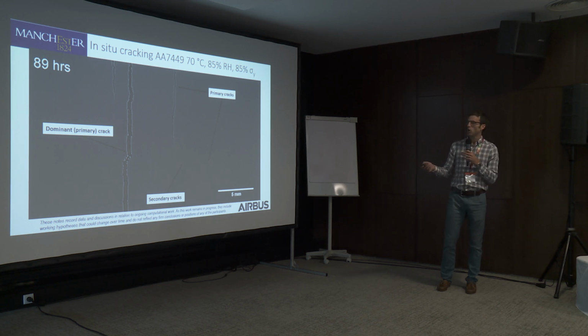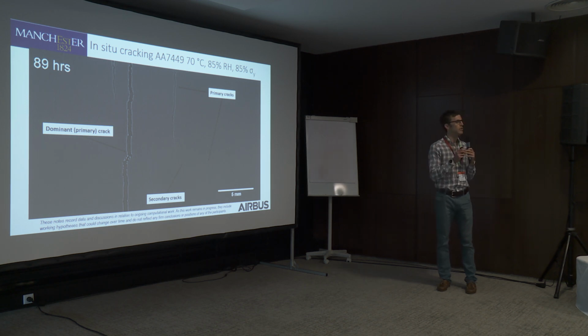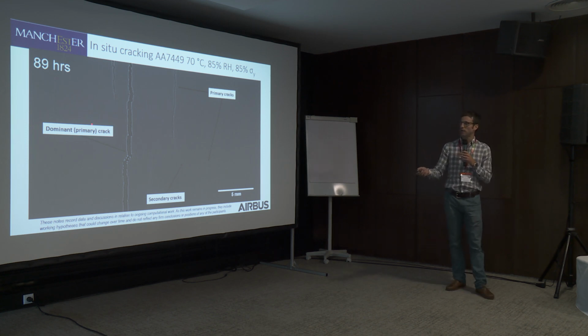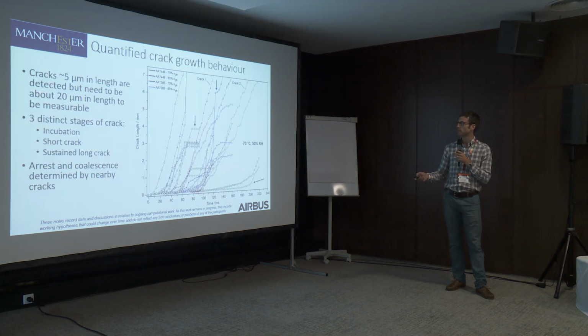We've defined primary cracks as those that have initiated independently, and the one that causes failure is the dominant crack. And then we have also secondary cracks. There's quite a population of secondary cracks which form in the K zone ahead of the primary cracks.